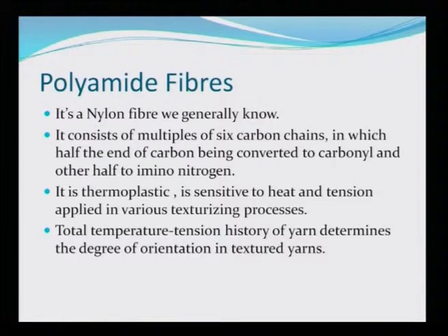Polyamide fibers, it's a nylon fiber we generally know. It consists of multiples of 6 carbon chain in which half the end of the carbon is converted to carbonyl and the other half into the imino nitrogen. It is thermoplastic, is sensitive to heat and tension applied in various texturing processes. So, the total temperature tension history of yarn determines the degree of orientation in textured yarns. So, you see that it has all very good qualities from the stability point of view.